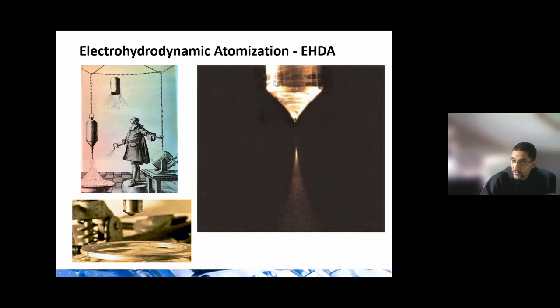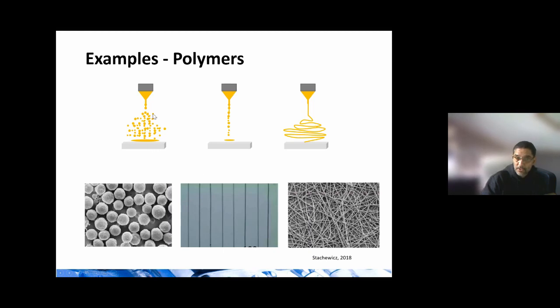If you imagine that our technology is now enough for the fabrication of nozzles with hundreds of micrometers, it means that I can use the same technique to produce nanometric particles. And we do this. You can also play a little bit with your concentration. For example, if you have a high concentration of a specific polymer in a specific solvent volume, you can suppress the breakup in droplets, as I said, for high concentrations. And then instead of droplets, you can have ligaments. So you can make droplets and you can make fibers.